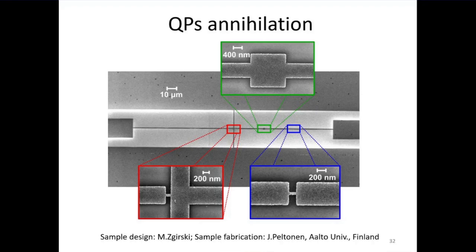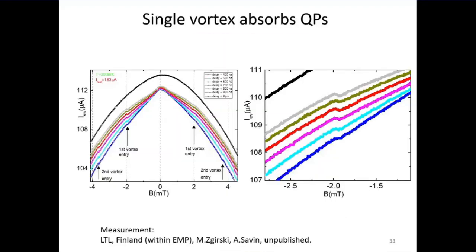This is a more tricky experiment, but still, if you measure now the critical current of the detector, you will find that the critical current as a function of field is suppressed. This is the Meissner feature. This is measured with no quasi-particle flux, without heating.